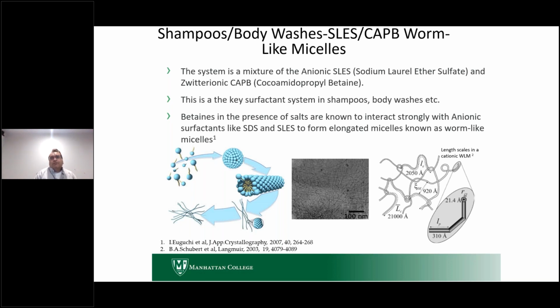And these then give rise to the strong rheological response that you see. With just the addition of salt, you can go from a system which is almost water-like in viscosity to something which is an extremely strong gel, and when you turn it over, it doesn't flow, because it's a very strong gel. And it doesn't end there, because if you keep on adding salt, you can lose viscosity.